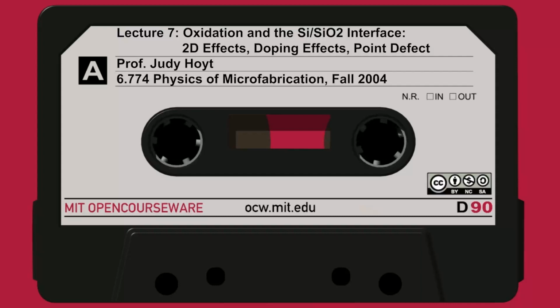And in fact, you see this. Look at the concave radii, all these dashed lines compared to the solid lines. The normalized oxide thickness at a given temperature, say here at 900 degrees, is a lot thinner for the dashed compared to the solid. So for a concave cylinder, he found a lot lower oxidation rate, oxidizing the inside of the cylinder as opposed to the outer surface. And so you see that difference right off, the solid versus the dash.